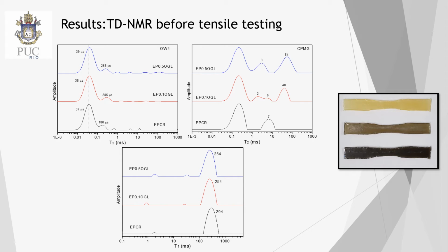Here we have the results of TD-NMR experiments before tensile testing, and we can observe that the addition of graphene provides an increase in the mobility of the polyamine matrix molecular dynamics, especially in the semi-rigid and mobile regions, with an increase in the transverse relaxation times. However, the rigid fraction does not show time and percentage variations, which indicates that the mobility conferred by graphene occurs preferentially in the regions of the matrix where the chains have greater mobility and space for the graphene to be allocated.